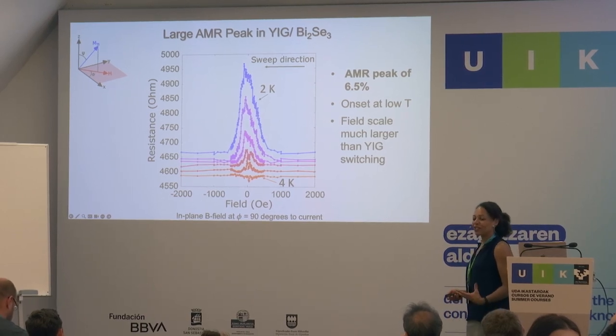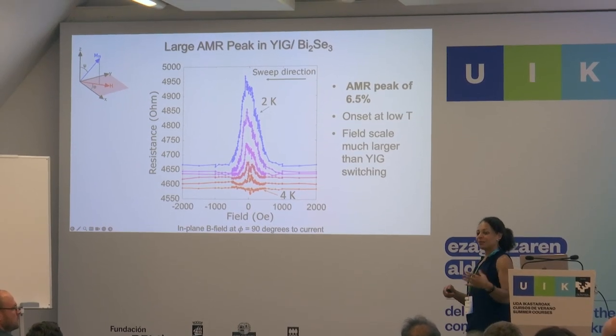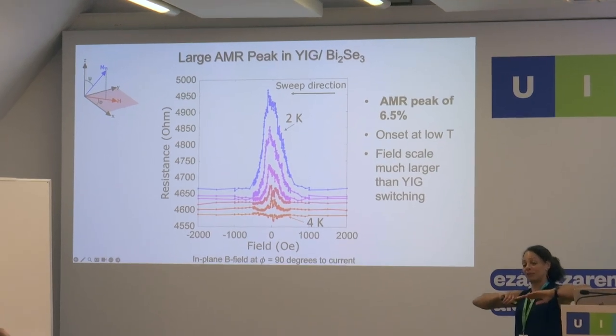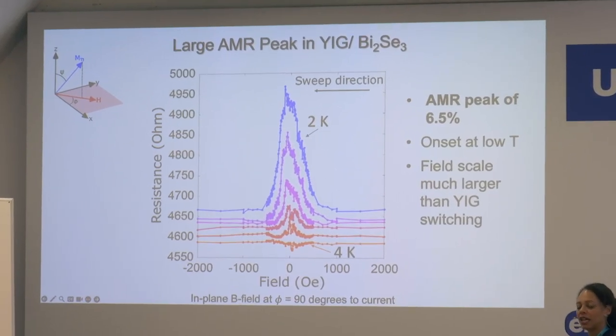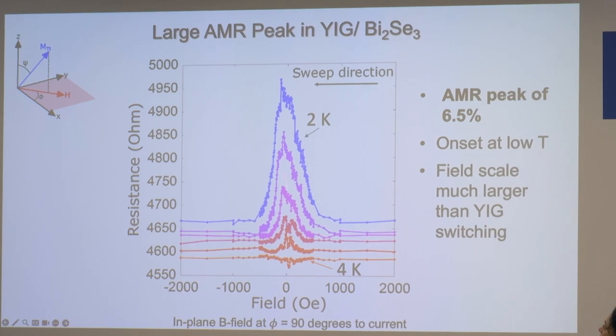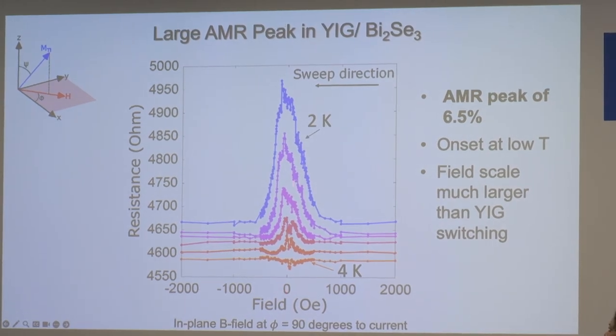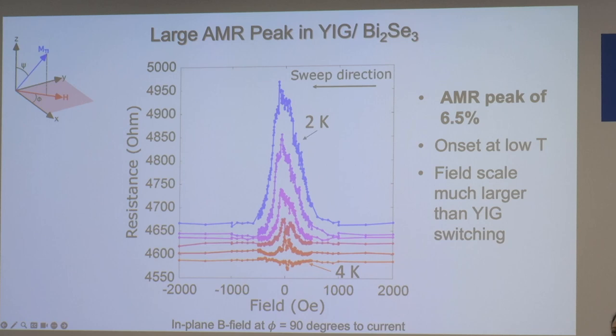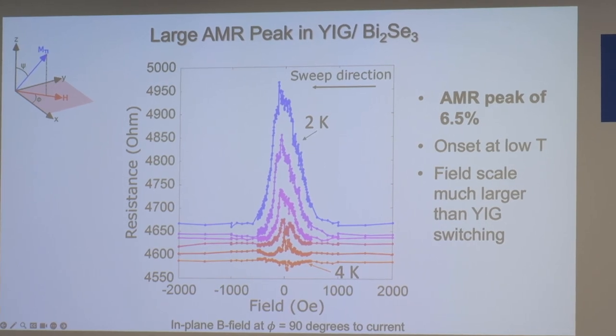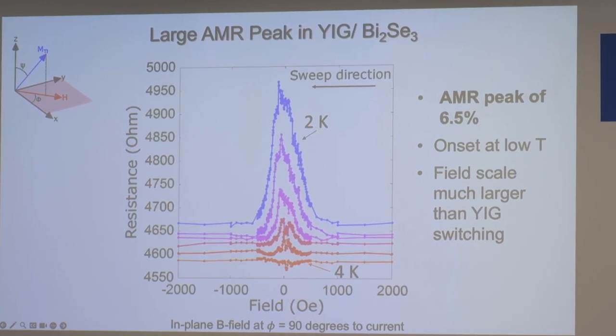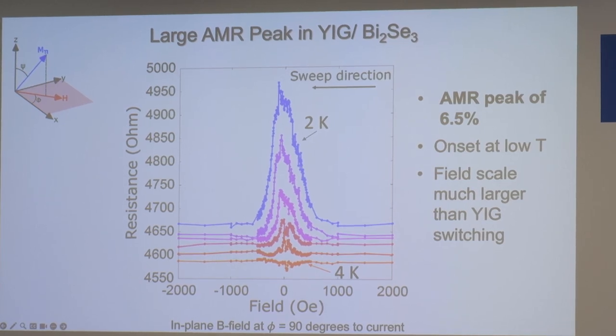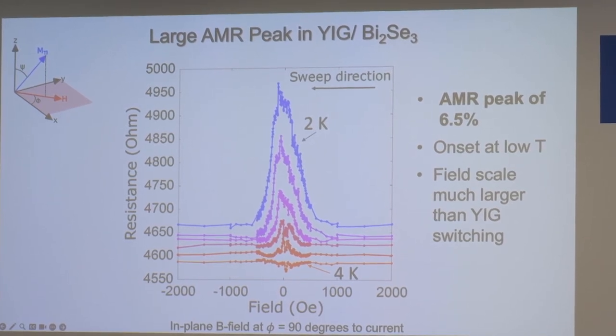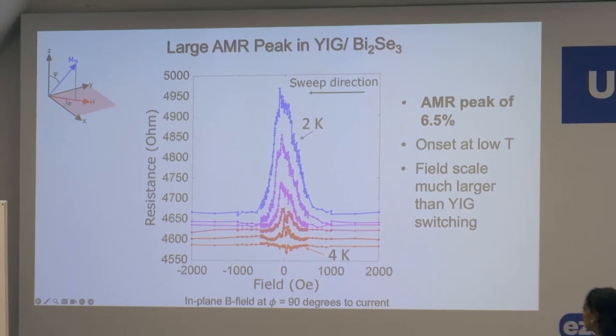On the other hand, if you're curious whether it's a surface state in bismuth selenide or some other semiconducting effect that should happen at any temperature, the fact that there's an onset at low temperatures is consistent with it being related to the surface states and not to just some other band trivial state that always exists in these systems. And the other thing we note is that the switching scale that we see is something like 500 oersted, which is 25 times larger than the YIG switching. And so what we believe we're seeing is switching of the surface state and not of the underlying material.